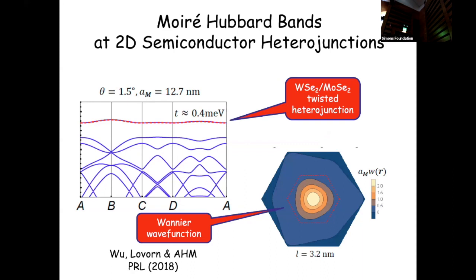And in the Moiré pattern, simply by changing the twist angle, you can change the period of that periodic potential. You can't very easily change the strength of it, except that by pressure you can increase the strength. And so, for example, at 1.5 degrees twist angle, you get one flat band, quite isolated from other bands. The electrons in this band are localized near the minimum of the potential for holes, which you can approximate by a harmonic oscillator. So this is basically a 1s harmonic oscillator level, and this looks very much like atomic physics.